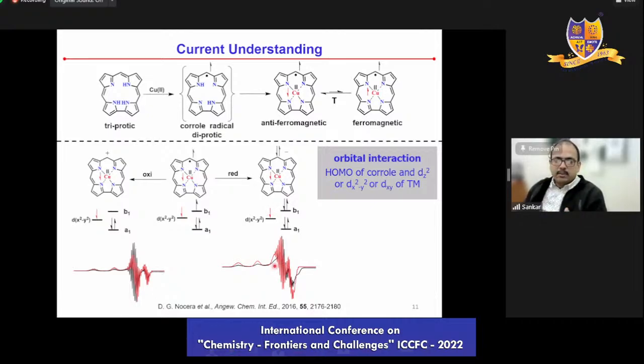So what it proves is that this study proved that the copper in corrole is staying as a copper 2 plus. It's not copper 3 plus, but because of the unpaired electron in the ligand, these guys behave like diamagnetic, but it is not purely diamagnetic. It is because of antiferromagnetic coupling that they become diamagnetic.